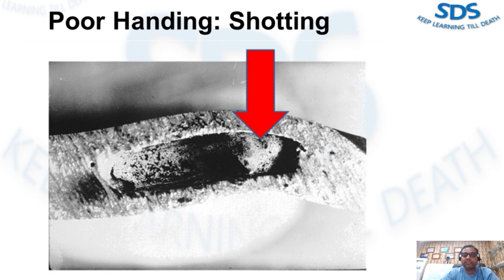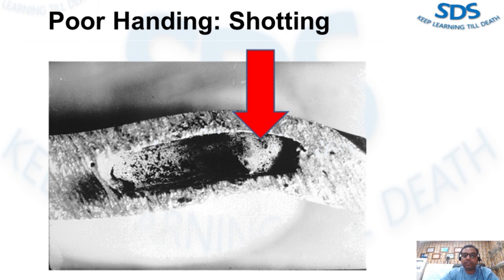Shotting: this figure is an example of entrapped gas caused by excessive graphite plunger lube and shotted metal. Note the ball of metal in the gas pocket. The shotted metal was caused by metal splattering up into the cavity, breaking away from the mainstream and freezing, then being surrounded by the mainstream of metal. This is often caused by a cold die and excessive velocity through a thin gate causing a semi-atomized effect. These small balls of metal run ahead of the mainstream, freeze, and are then engulfed in the main mass a few milliseconds later. They show up on the machined surface as shiny spots, since the balls of metal are encased in an oxide film.